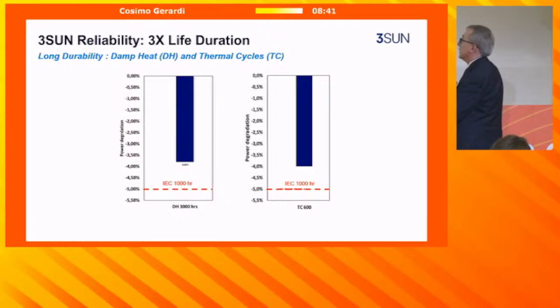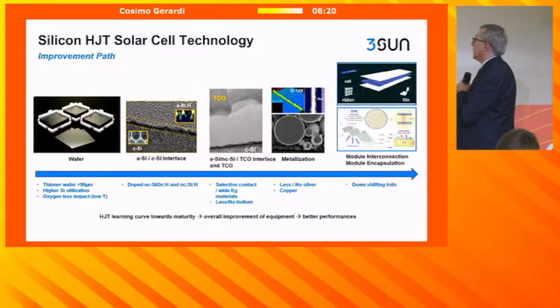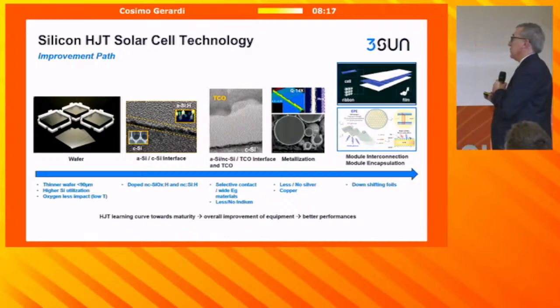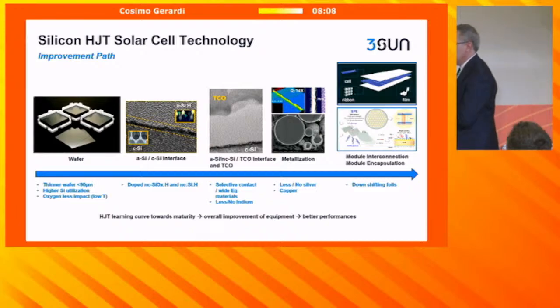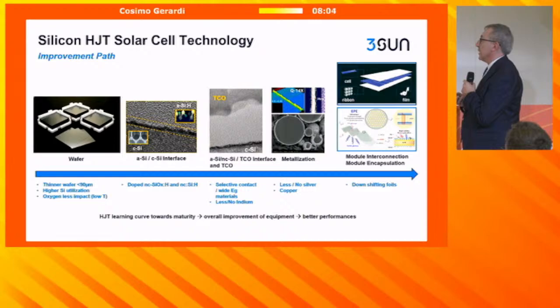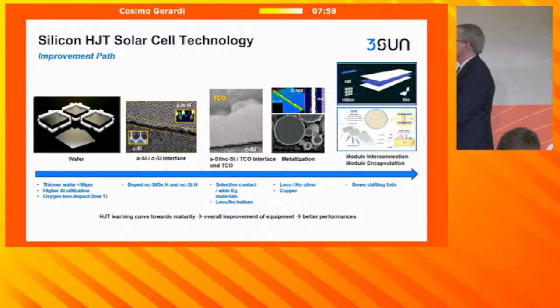That means 3 times what is stated in the norms for the 1,000 hour. We can achieve 3,000 hours for the heat test and 3 times the thermocycle while keeping within the maximum degradation that is 5%. And what is the path for improvement of the heterojunction technology, which is of course improvement of the wafers. That means reducing the wafers that can help in reducing costs, and the fact that oxygen has less impact because the process of heterojunction is a low temperature.